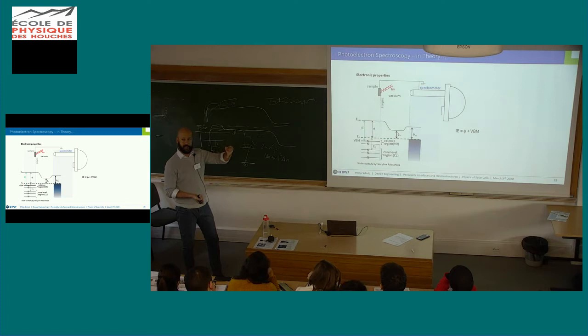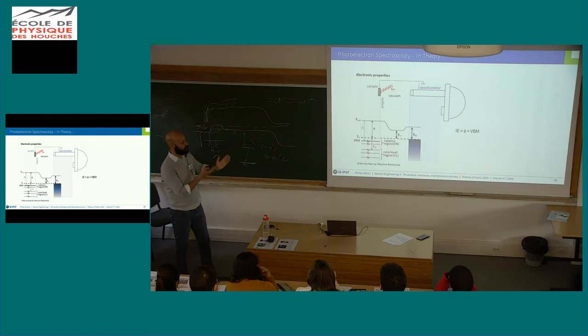So the technique cannot be used to measure the absolute vacuum level, but you get only these reference or relative vacuum levels as a contact potential difference, more or less. So the principle is very close to that. Of course, this only works when the Fermi levels are aligned. So this needs to be reasonably conductive, and you need to bring them onto the same potential.